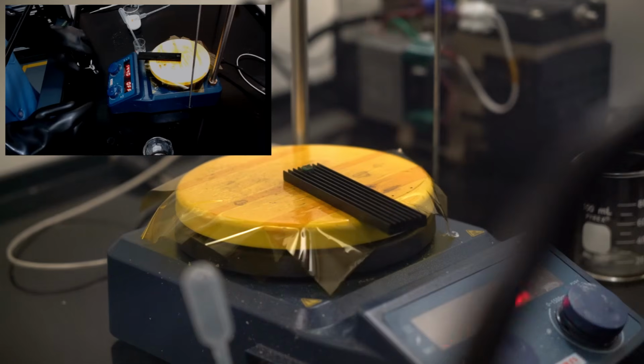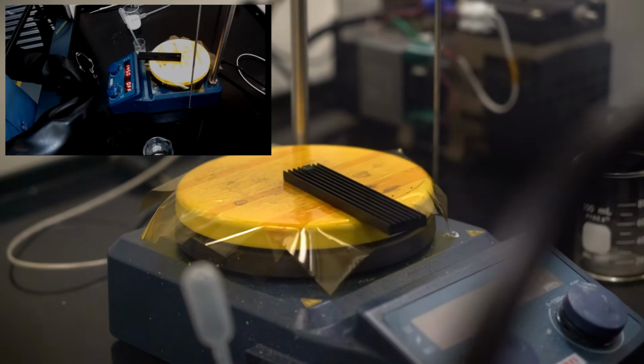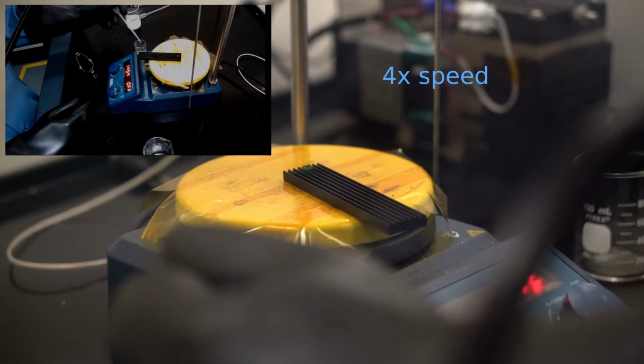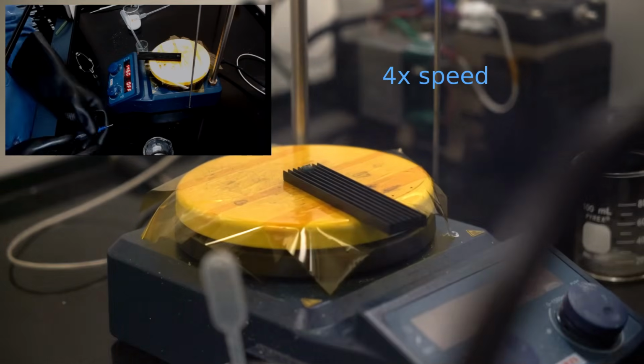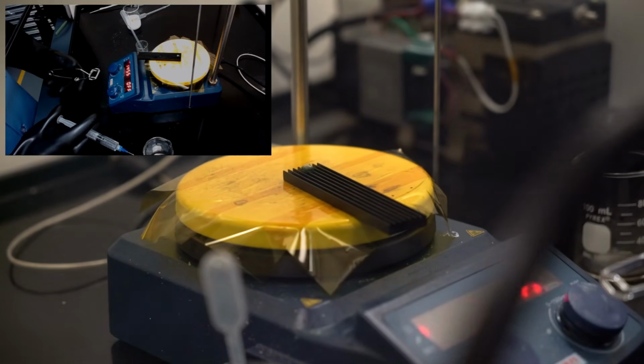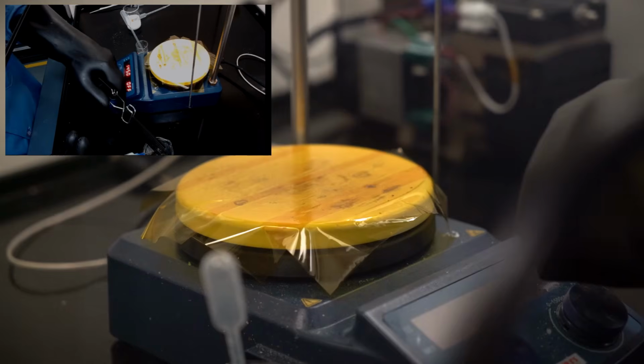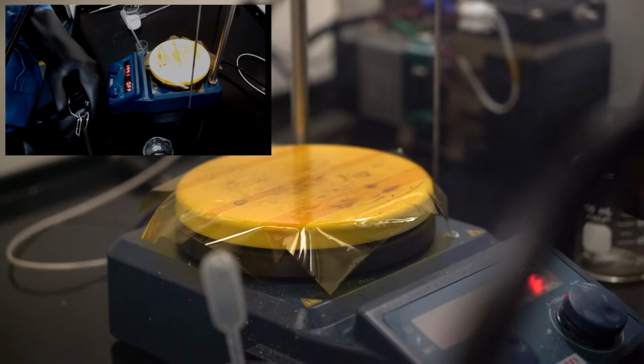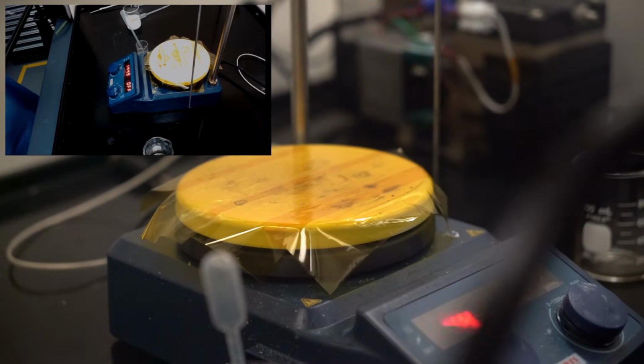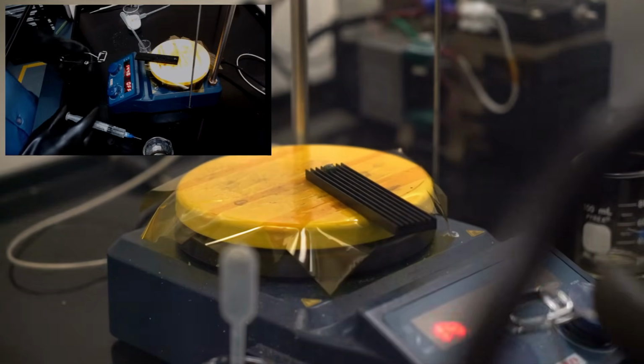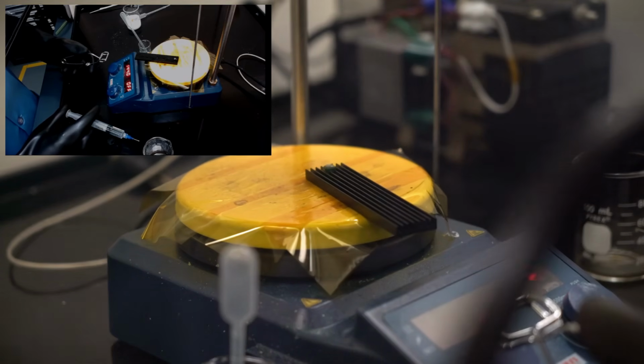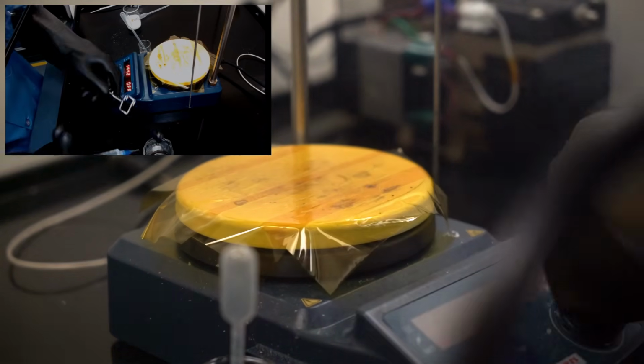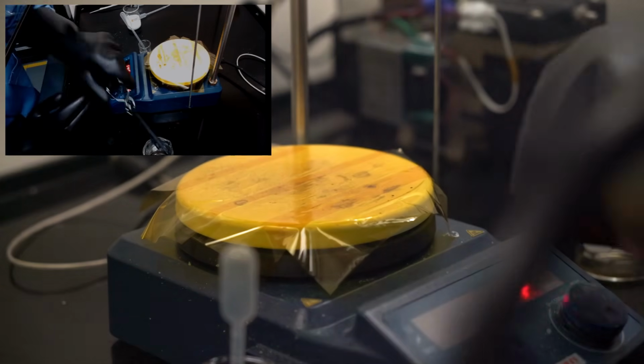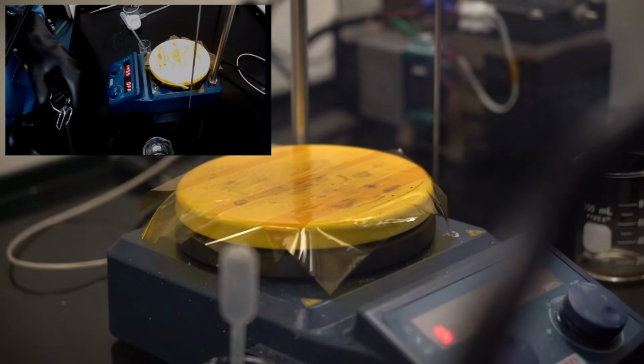So now I'm just doing one last inspection and checking to see. It looks like I think I'm going to do one more drop of acid and then call it done and ready to take off. And then after removing it from the heat for the final etch cycle, then off camera I did a full aqueous clean, which is okay since we're not going to be doing more acid etching at this stage, and then sonicated a little bit to get the last of the debris off, which is a little tricky since you don't want to damage the bond wires, but a few seconds of sonication will make a big improvement in surface quality.